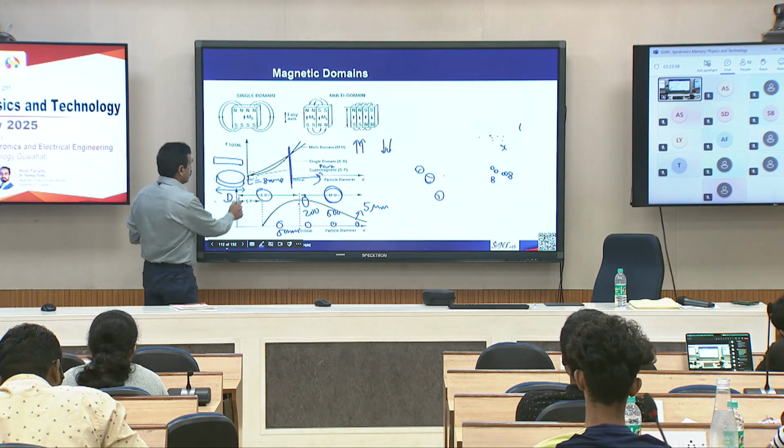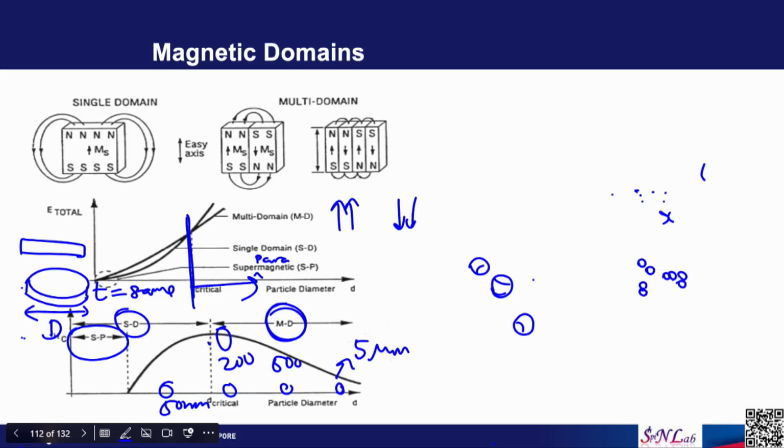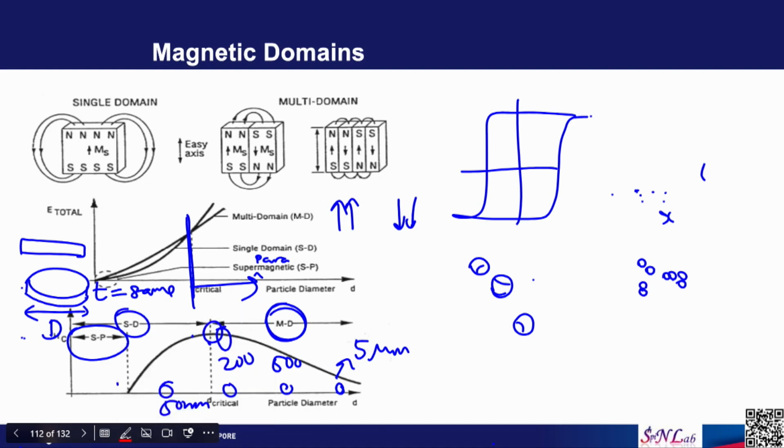So, when you are in the super paramagnetic region, the particle will not have coercivity, because they are fluctuating as a function of time. The hysteresis loop will vanish. So, in the normal case, let us say you measure the hysteresis loop here, you will have coercivity like this, but if the particle size is too small, then there is no hysteresis loop, it will be like this.